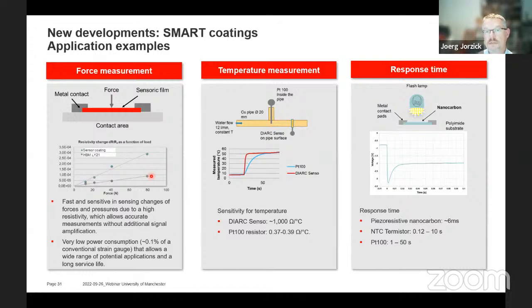So that is one very interesting thing. Looking at temperature measurement, again, what we did here, we had our sensor. Diarc Senso is the brand name for this coating. It was applied here in a water tube, a tube where water was flowing through, and we compared it with a classical PT100 element, and then we looked at the response again, and we see that the coating sensor is responding much faster to the temperature change of the water compared to the classical sensor. So that means not only more sensitive, as seen in the force measurement, but also a faster response time.